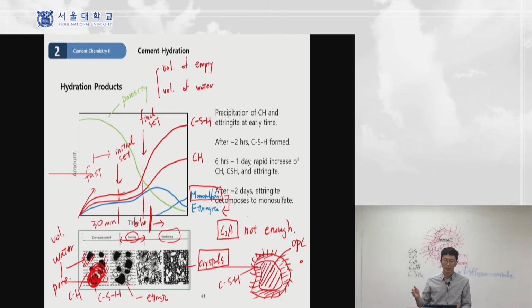The ASTM standard, Korean standard, or European standard propose how to measure the setting time. Setting is something between a true solid and a liquid, you can imagine. And why do we have this kind of set behavior? Because basically this is a liquid to solid transition, and that transition is due to the formation of calcium silicate hydrate and also ettringite crystal. Calcium silicate hydrate and ettringite are the dominant phases for concrete to have some strength. But from a volume perspective, calcium silicate hydrate will occupy much of the volume, 60 to 70% of the volume of the given system.